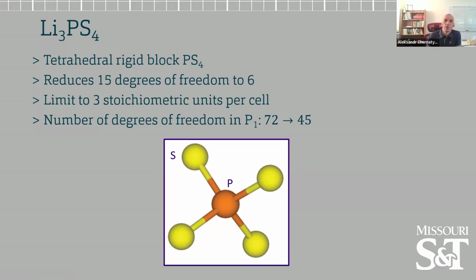this process. We're going to limit this to up to 3 stoichiometric units per cell, and this limit is simply to limit the time spent on the first principles calculation. So again, this limit only comes from the computational abilities available to you rather than anything else. There is nothing fundamental about that. And for the larger systems, for the 3 stoichiometric units, if you happen to be in the group P1, which doesn't put any additional constraints or restrictions, then we're going to go from 72 to 45 degrees of freedom, which, one can argue, is not a terrible degree of reduction, but again, this thing blows up exponentially and even worse, so that is reasonably useful.